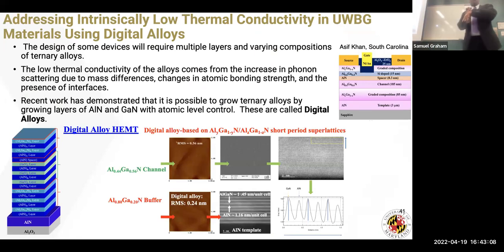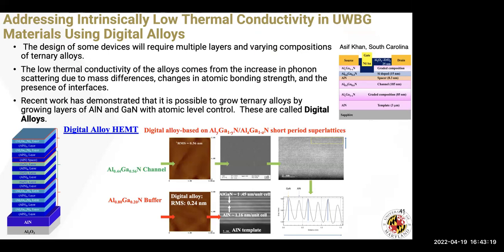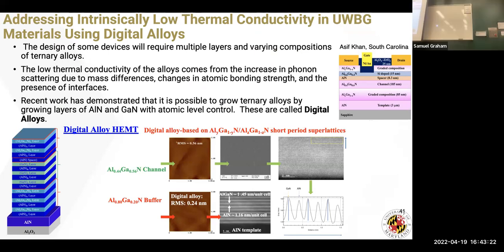So the last part that I want to talk about as I wrap up is, we always complained, or at least I've been complaining, that the thermal conductivity of these materials is quite low. Is there something that you can actually do to increase the thermal conductivity? And so there's a concept called digital alloys that I want to talk about now. When you typically grow a material like aluminum gallium nitride, it basically has a crystal structure that is the same as gallium nitride, but you don't necessarily control where all of the aluminum goes inside of the lattice. And so a digital alloy is basically taking a layer of one material, growing it, and a layer of another material, growing it. And so you alternate these.